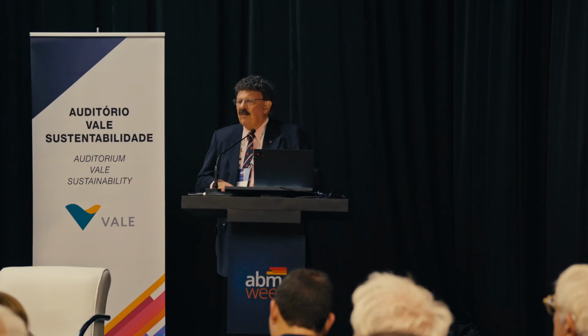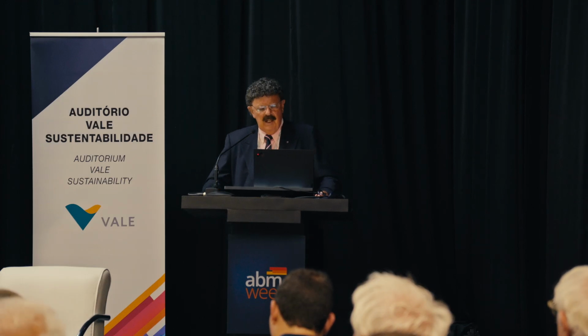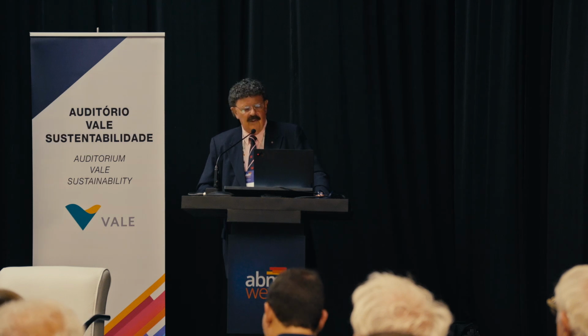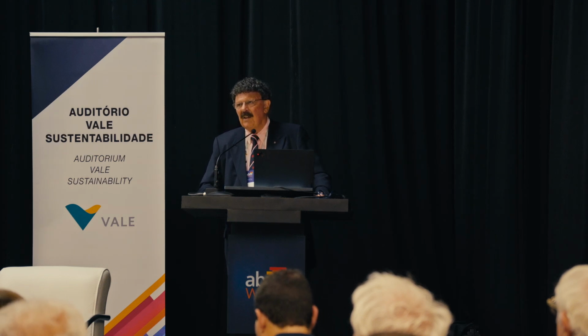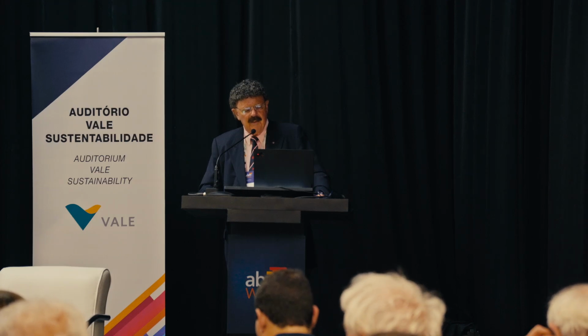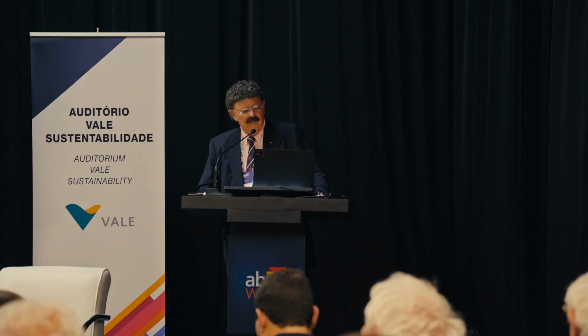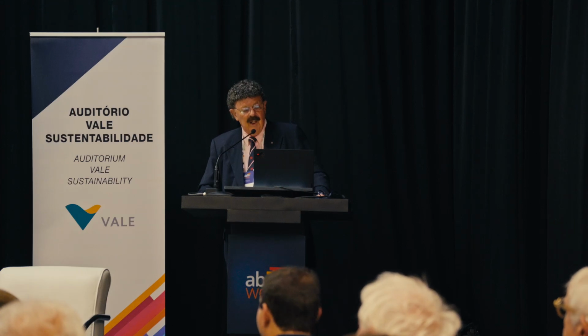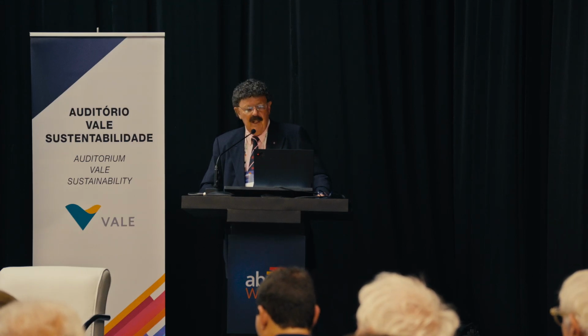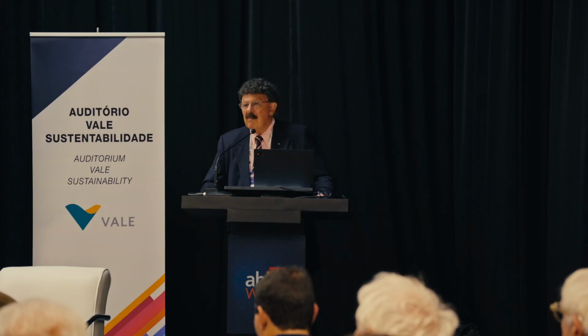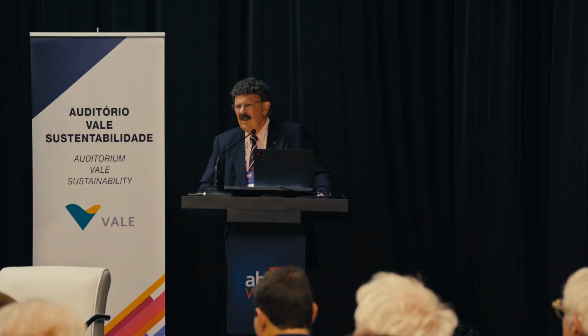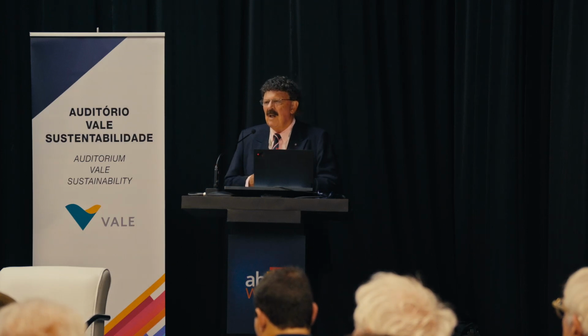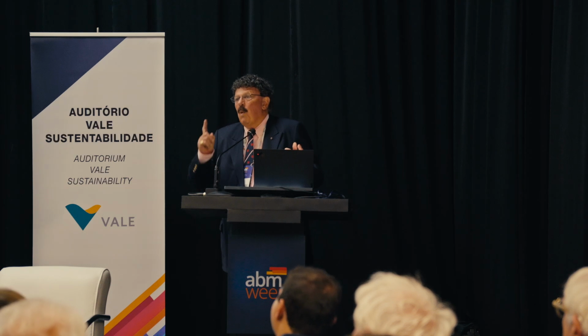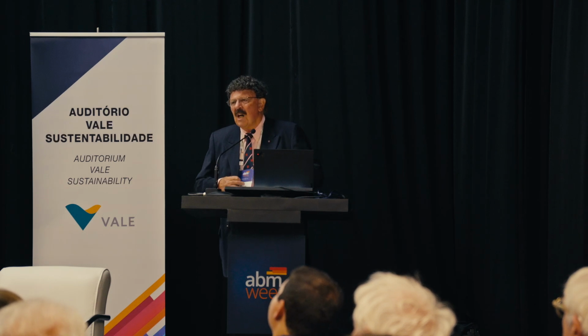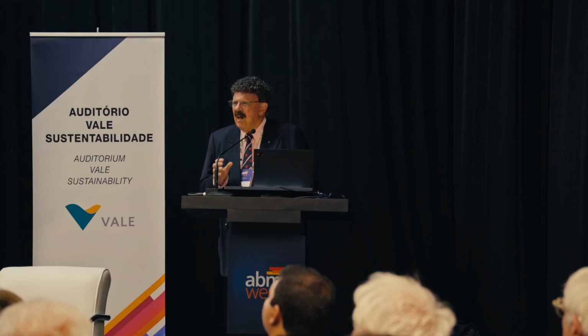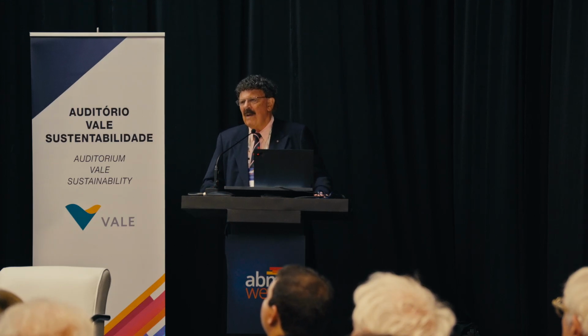And what interests me, I'm a fracture mechanics person, I was interested in their toughness. And these are R curves, resistance curves. They're the J integral, which is a non-linear elastic parameter, plotted against the crack extension. And these, again, the room temperature has high toughness, but the very low temperature has really high toughness. And these alloys have toughnesses that are above 300 megapascal root meters. Now, these are enormous numbers. Most steels don't get much above 100 megapascal root meters. Silicon is 1 megapascal root meter. These are up around 300 at liquid nitrogen temperatures. So they are fascinating alloys. They have remarkable fracture resistance.